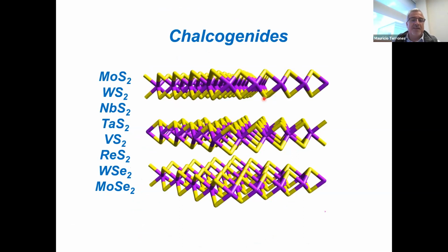So basically, this is what we call a monolayer of a chalcogenide, but in principle, there are 3 layers. So you have a metal layer here, and it is sandwiched by a chalcogen atom. So it could be sulfur, selenium, tellurium, right? So it's having a sandwich, right? So you have the bread on top and bottom, and you have the ham or cheese in the middle. And this is one monolayer. These are van der Waals forces that keep the layers together, but you can exfoliate, and then you can get many interesting properties when you go to the monolayer regime.